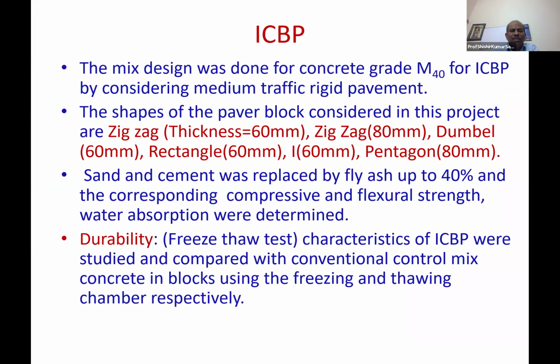The mix design was done for concrete grade M40, considering medium traffic rigid pavement, because we thought of ICBP to be used as pavement. Whatever you are seeing around is M20 or M30, not M40. We have tried M40 as a paving material, to make it a medium traffic rigid pavement material.